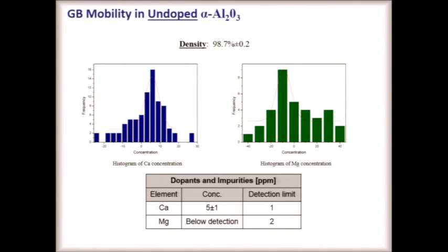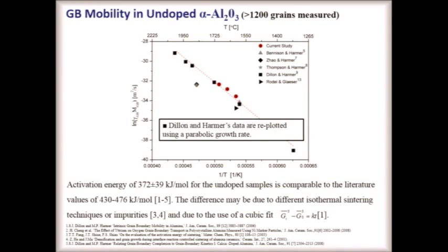Okay, we sintered this to 98.7% density, and then we did a series of growth experiments where we measure the grain size as a function of time and temperature. What I'm showing you here is our data at different temperatures already translated to mobility. I'm skipping through all the details, and I'm comparing it to the data that's in the literature, including the Harmer data, which Shen Dillon was kind enough to give us his raw data, because we had to recalculate this and to do it actually in a parabolic fashion. And it fits out fairly well. So yeah, it's nothing really exciting, but it's something that we had to do, and at least we felt good that the data was falling in line with some of the better data that we saw in the literature, okay?